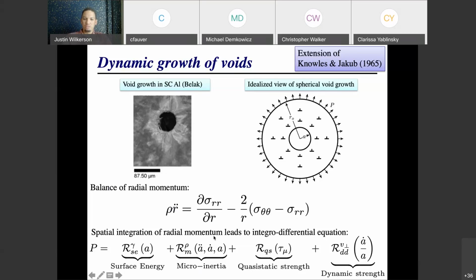Then I have this microinertial term, which essentially accounts for the inertial resistance. So as I have this mass around the void and I want to accelerate that away, there's a resistance to that, so that's accounted for in this term. It's essentially this rho r double dot integrated. And then I have 2 terms which come from the integration of this last term in the balance of radial momentum. And like I said, that is the deviatoric stress there. So those account for the resistance to void growth due to the resistance to plastic deformation of the matrix material around it.